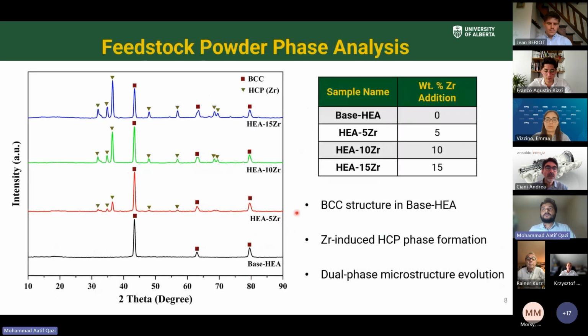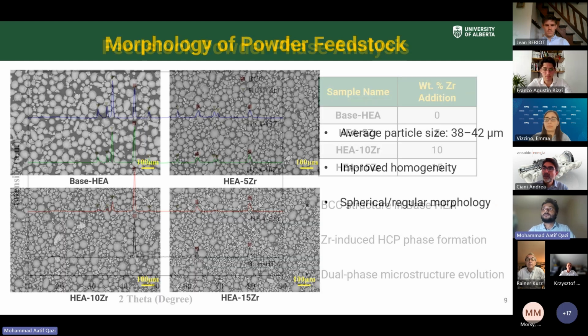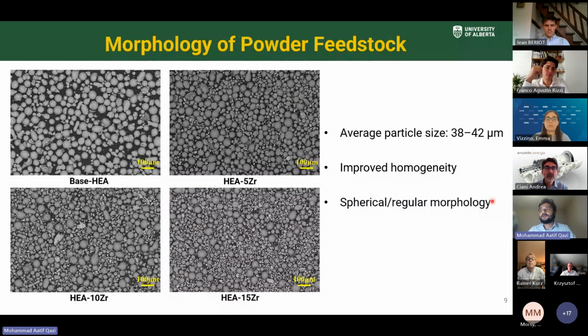The XRD analysis of the powder shows a BCC phase and an HCP, Zr-induced HCP phase. The SEM analysis of the powder shows regular and spherical morphology with average particle size ranging from 38 to 42 microns.